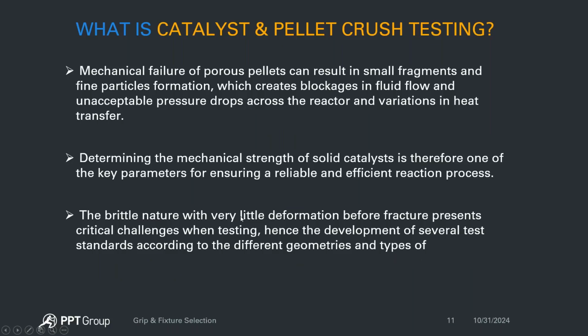There are also mechanical failure properties that will cause small fragments and fine particles forming, which essentially creates blockages in fluid flow, especially in the oil and gas, oil refinery and petroleum industries. And this is unacceptable, which essentially will cause pressure to drop across the reactor and create other variations in heat transfer. Again, determining the mechanical strength of solid catalysts is therefore key.